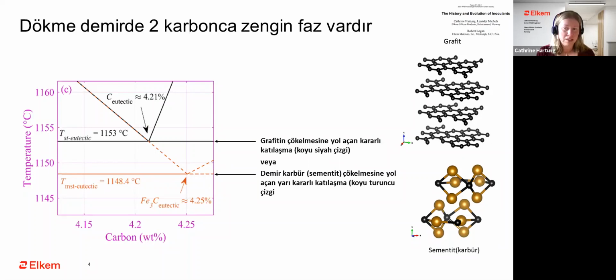So to avoid cementite, the solidification has to start and preferably end between these two lines that you see here. And the closer you are to the eutectic, the black line, the more safety you have against forming carbides. And it is here that nucleation and nucleation potential comes in.